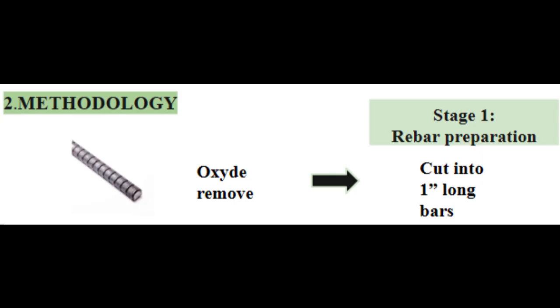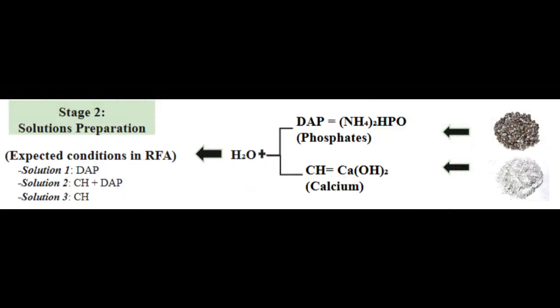Method: in this study, 1 inch long and 3/8-inch diameter steel bars underwent a polishing process to remove potential oxide layers. The objective was to analyze the effect of 3 solutions containing the main expected compounds in treated recycled aggregates on reinforcement steel bars. The prepared solutions were DAP plus water, CH plus DAP plus water, and CH plus water. DAP represents diammonium phosphate. CH represents calcium hydroxide, and these compounds simulate the effect of treated recycled aggregates, either separately or in combination. In this case, DAP plus CH.